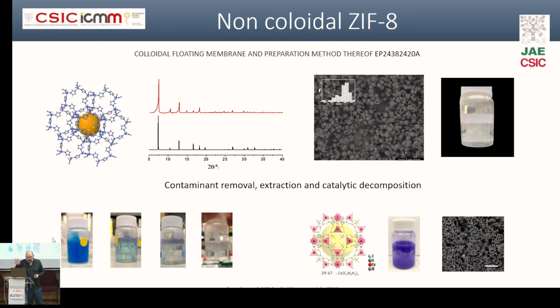The interesting feature of this material, that was at the beginning unexpected, then we understood, is that it floats. It generates an interface on top of the surface. So we can recover that material easily from the top of the liquid. And it makes the use of nanoparticles more feasible in the real world. So we will try to move forward together with Pilar to see if we can do something real with this.